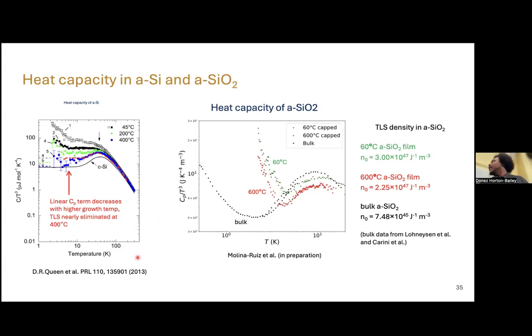All right, and just kind of showing a little bit of this heat capacity data from the past. We saw that looking at silicon, when we have the crystalline silicon, this is the heat capacity divided by T cubed. So if it's a crystal, heat capacity should go as T cubed, and that's what we see here. The curve is flat as we get closer to zero temperature.